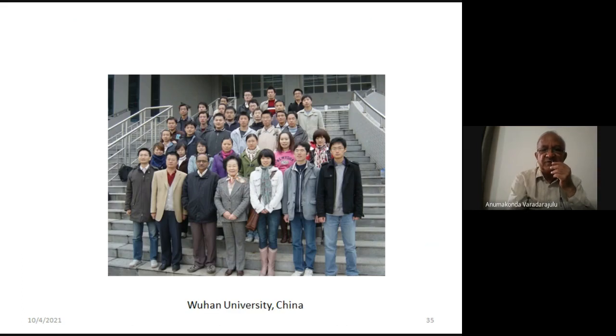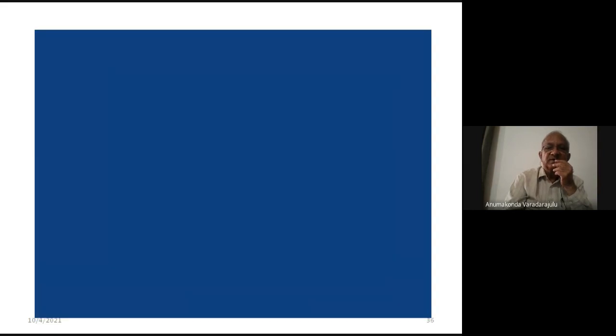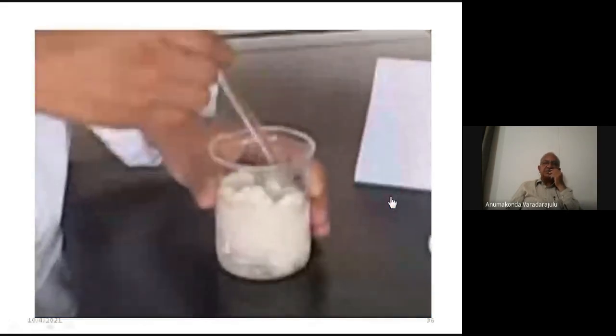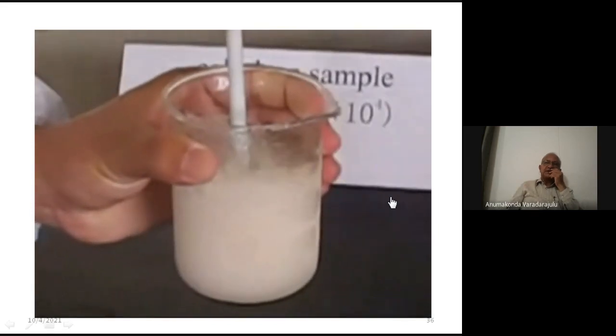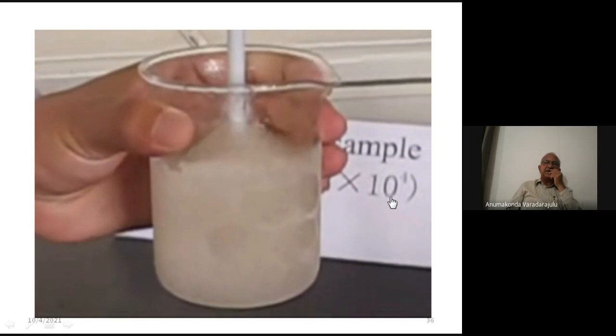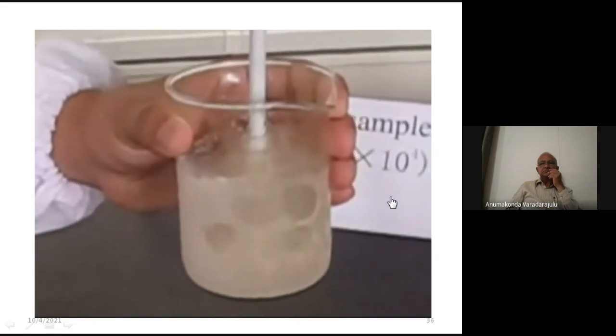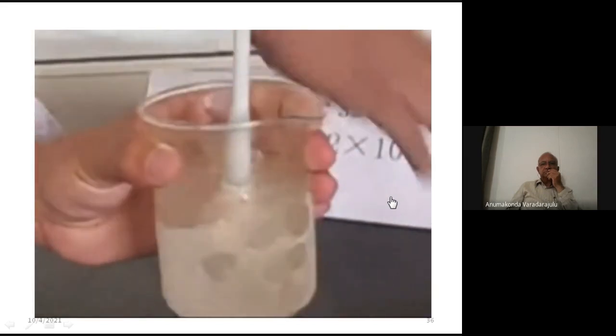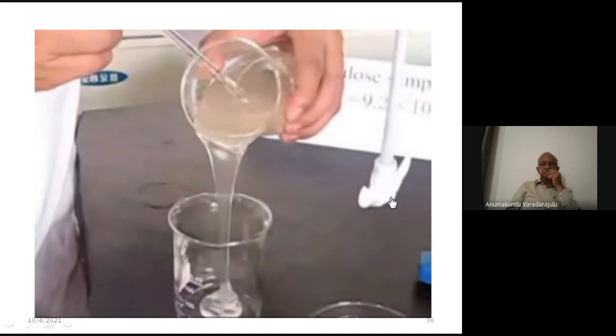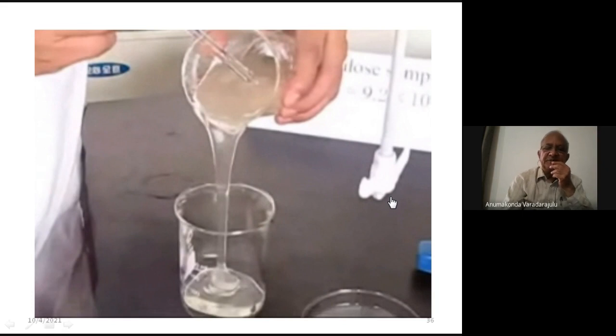This is real time, what we carried out, the synthesis of this particular solvent in the Chinese Academy of Sciences. So this is real time. I have added this cotton to that pre-cooled solvent at room temperature. Now, stirring it, you can count down the time. Within 2 minutes, you will be getting a clear solution. Yeah, within 2 minutes you can be getting it.